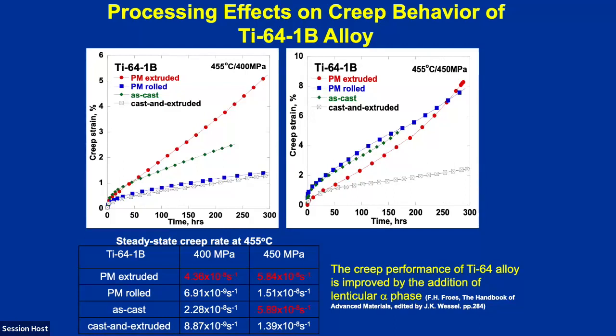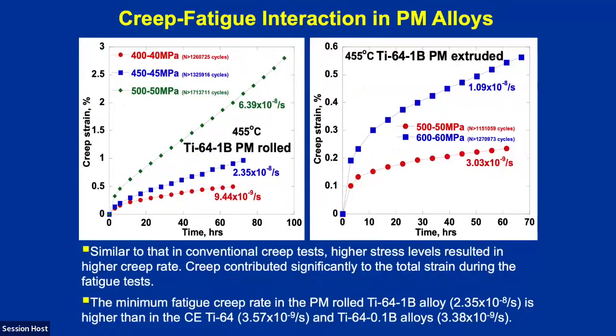We've done a bunch of tests to identify what the activation energies were, tried understanding the deformation mechanisms, and published that in different articles. But it's improved by the addition of the lenticular alpha phase. We know that from past research, and therefore that's an important component to control the alpha morphology. But if we look at the fatigue properties, we were measuring the strain during the fatigue tests, and it was at 455 degrees C.